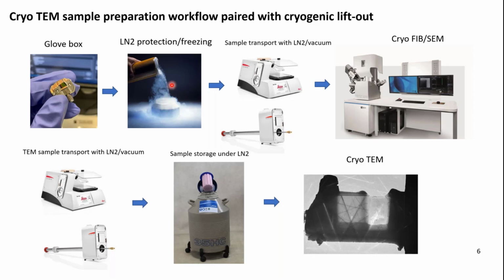the sample. And you can put your samples in the liquid nitrogen working station of the Leica microsystem, and the vacuum transfer tool below here is used to transfer the quenched sample to the cryo-FIB SEM stage. Once TEM sample preparation is done, you can take out the sample using the same vacuum transfer tool. Finally, you can store samples in liquid nitrogen until you perform cryo-TEM analysis.